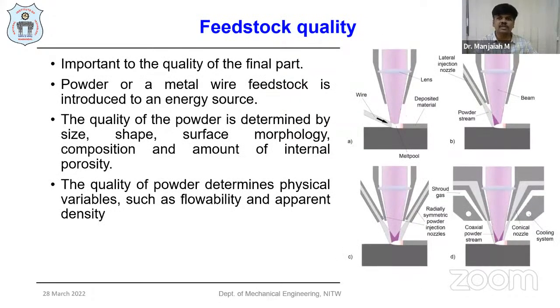The other barrier is feedstock quality, as well as the powder quality and powder characteristics. If you talk about the feed quality, whether we are feeding in the form of a wire, a ribbon, or a powder, and how we are feeding the powders in the DED system, whether by additional lateral injecting nozzles, radially symmetric nozzles, or coaxial nozzles, these all affect the quality of the components and the final part, as well as the material feedstock when it is introduced between the energy sources. Because when the melting takes place, it depends on how the melting takes place from the feedstock.